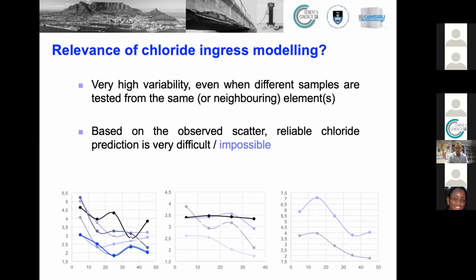So what we can see from this is that we got a very high variability of test results, even when different samples are tested from the same or neighboring elements. And based on the observed scatter, reliable chloride prediction is very difficult, if not impossible, to achieve, which once again speaks to the point that it is actually quite difficult to model durability in a way that gives us a quantification of the service life. This points out that all these more complicated methods to design for durability might be slightly, let's say, inaccurate. So when we use our service life models and diffusion models to model chloride ingress, the question is, how applicable are these really in the field?